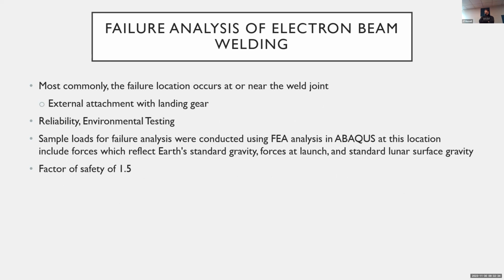Regarding the failure analysis for the electron beam weld, we found that the failure location would likely be at the point or near the point of the weld joint. And this would be its external attachment with the landing gear. So to test the failure analysis for this specific location, we had plans to conduct further reliability and environmental tests if we continued along with this design.